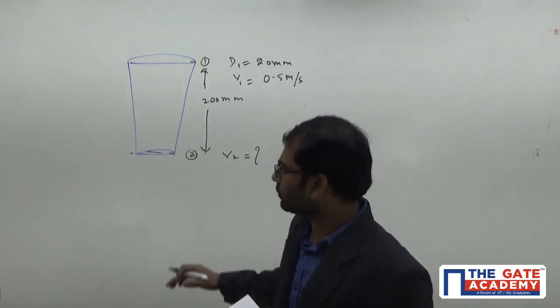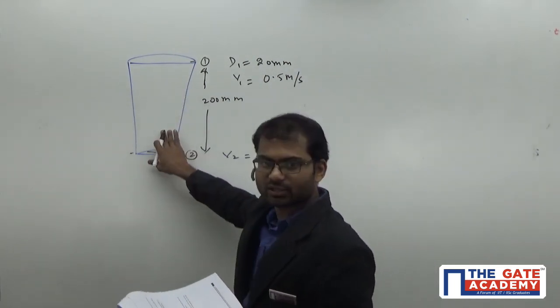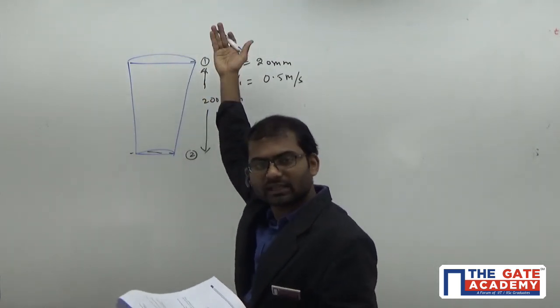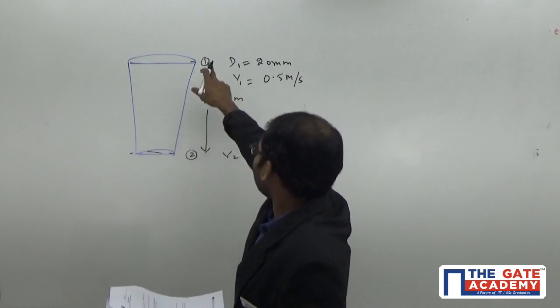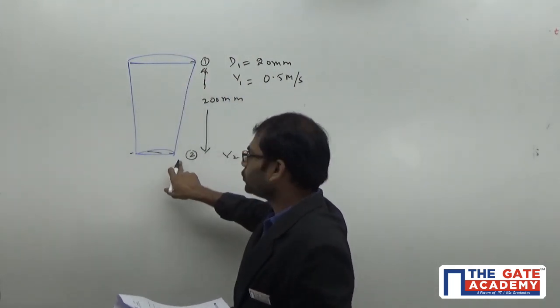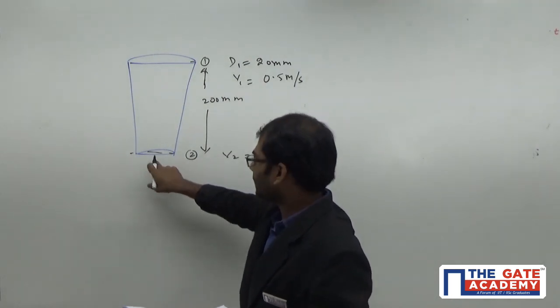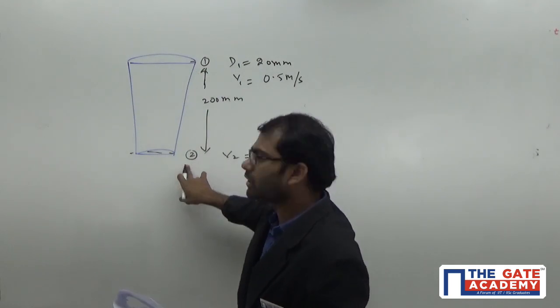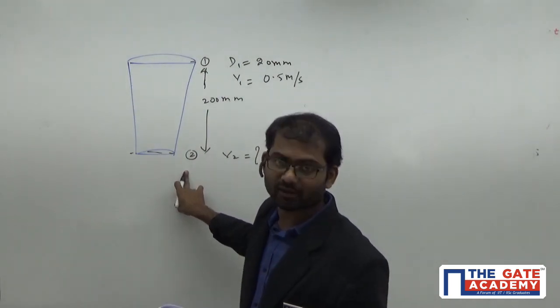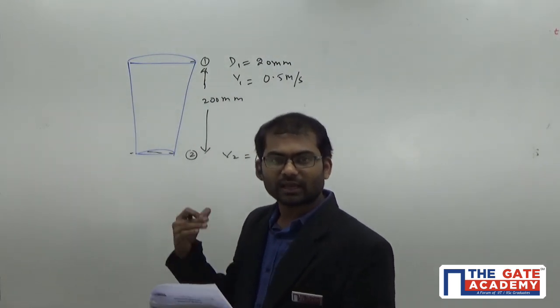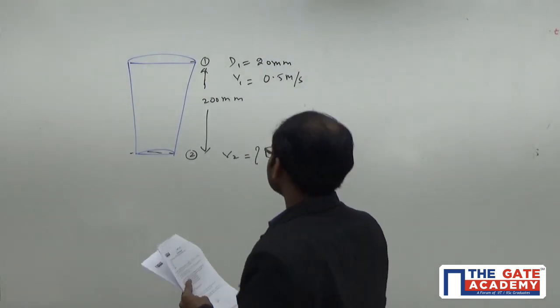To avoid that, we make sure that inside this region, pressure will be equal to or greater than the atmospheric pressure. So, P1, that means area at point 1 is exposed to atmosphere, and P2, which is inside near the casting, pressure must be equal. At least minimum conditions, they must be equal, then only gas will not be coming into the bulk of the casting. So, pressure must be same here.